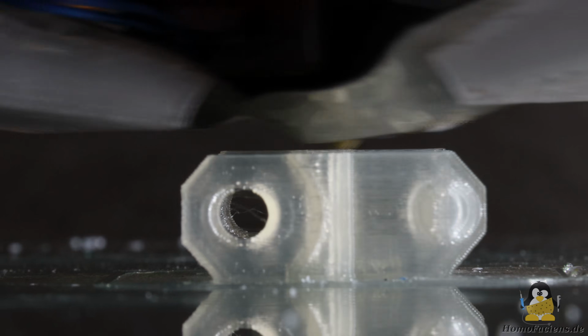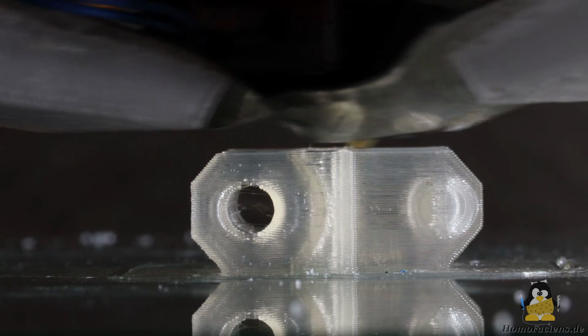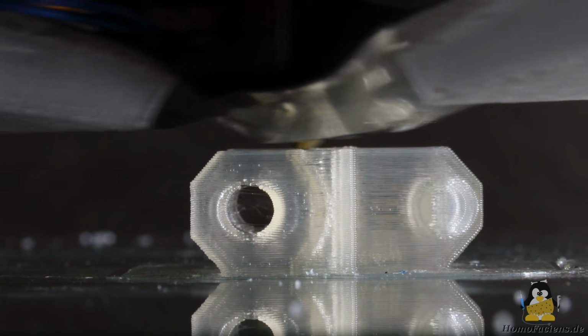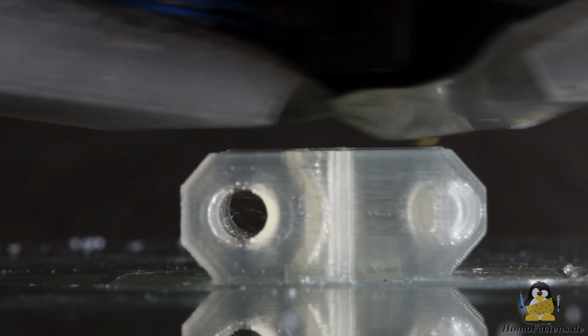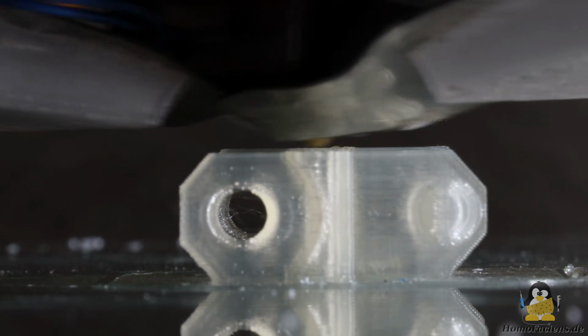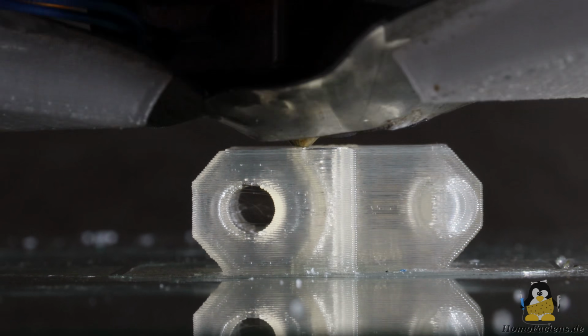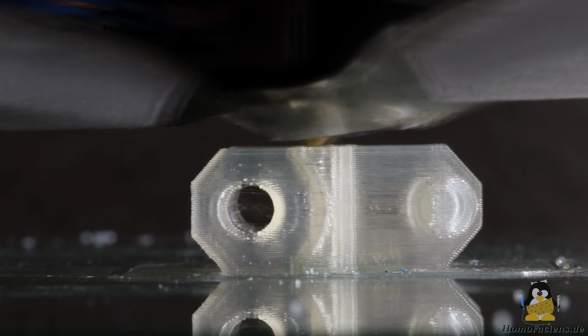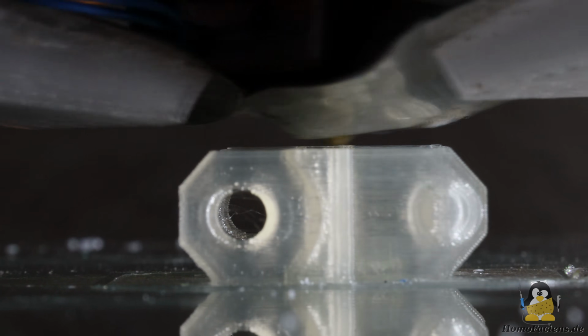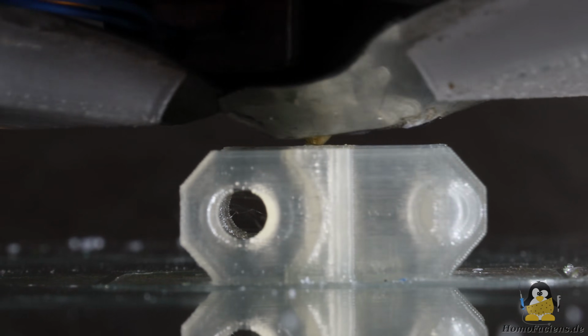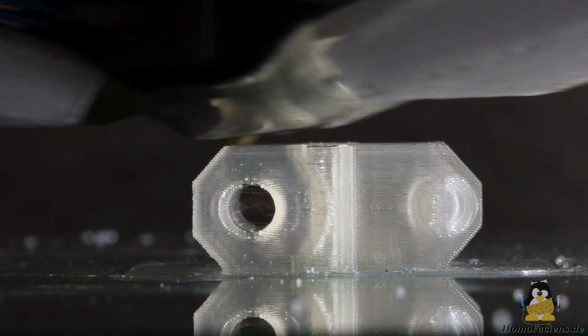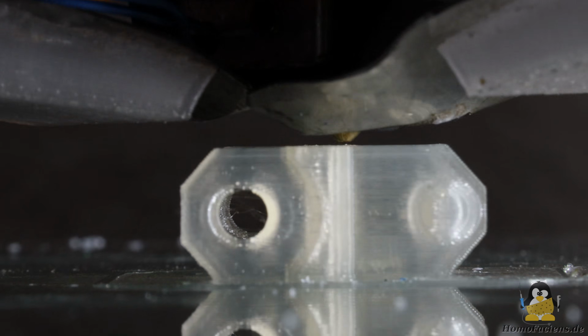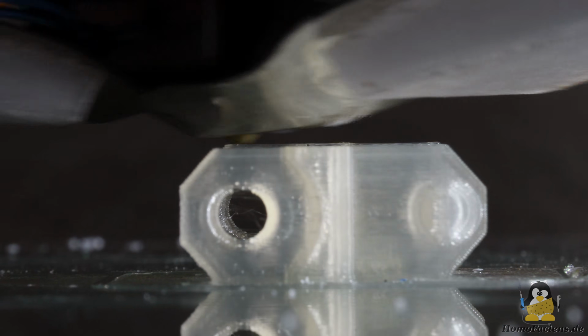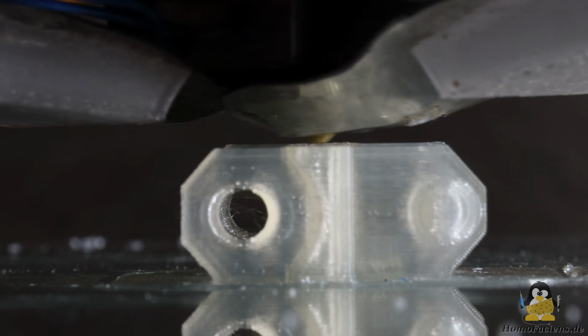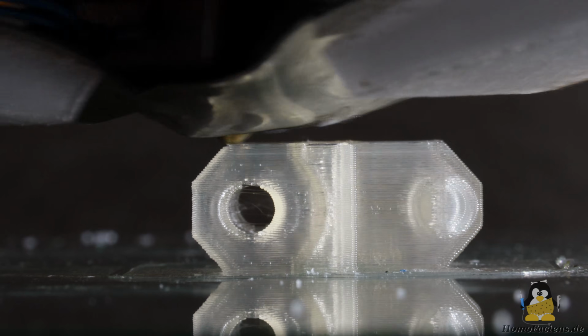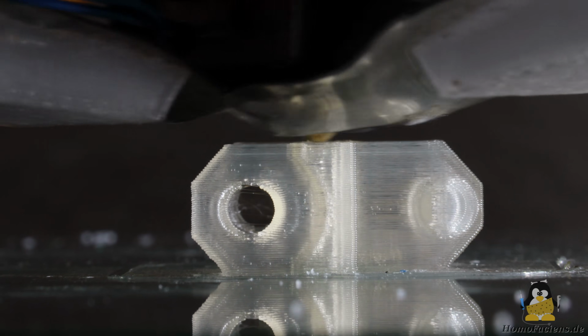A smaller gap should ensure better powder feed. However, the slippage does not vary while the material is being fed to the nozzle. We saw in the previous experiment that the fine powder was forced through the tube very uniformly. Consequently, the extrusion process can be controlled very effectively, yielding the best print result of the entire test series. The transparent PLA shows no gaps, neither on the outer walls nor in the internal structures, and contains only a few tiny air bubbles.